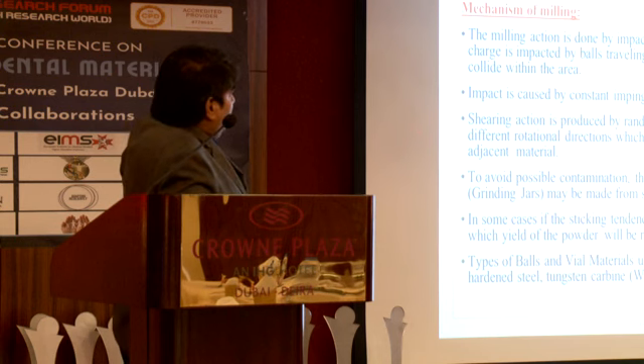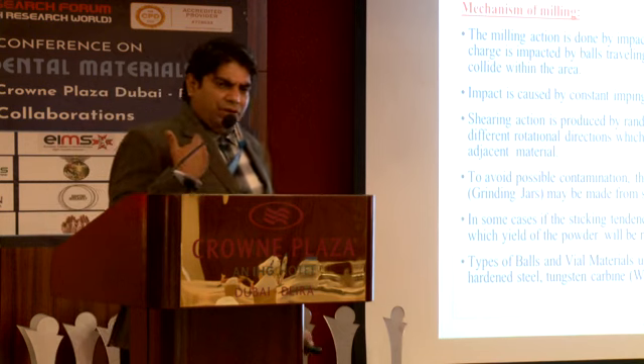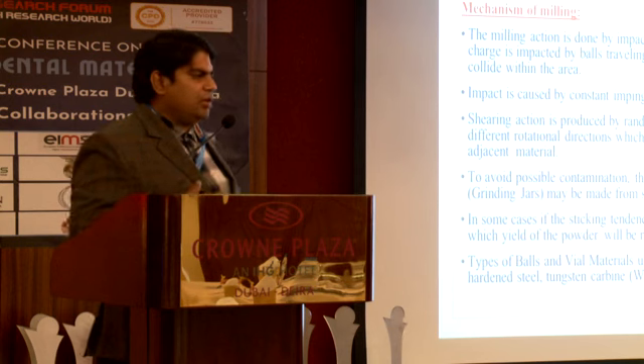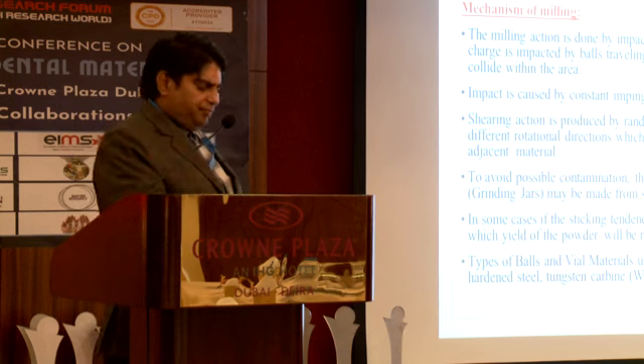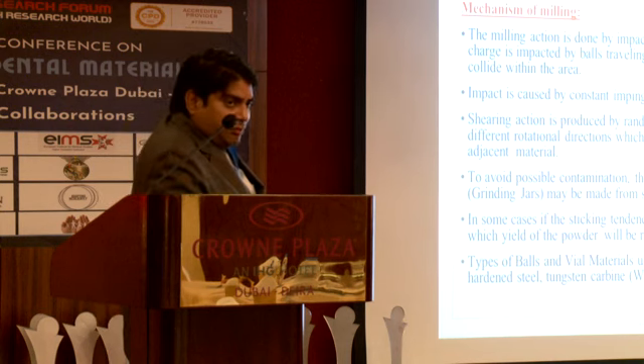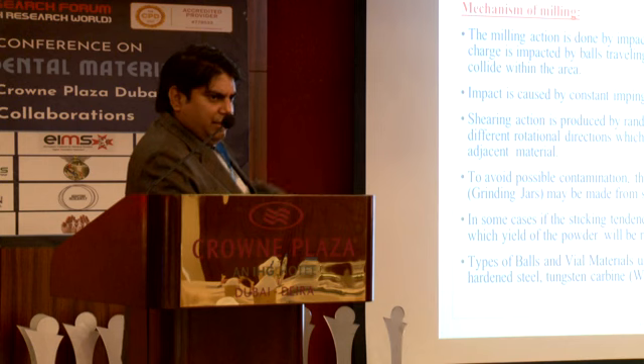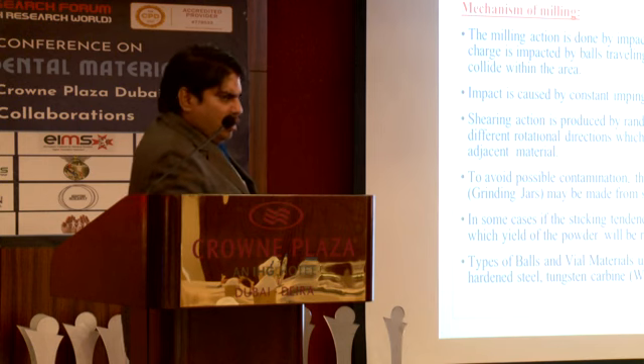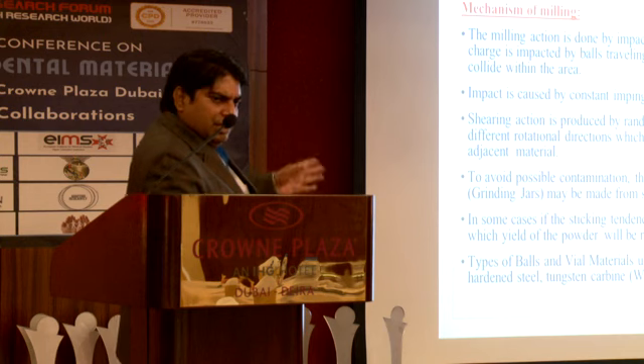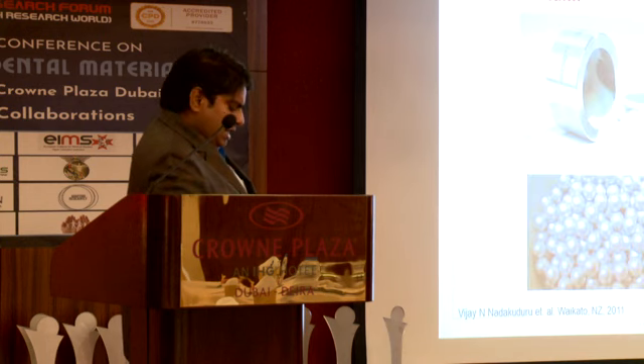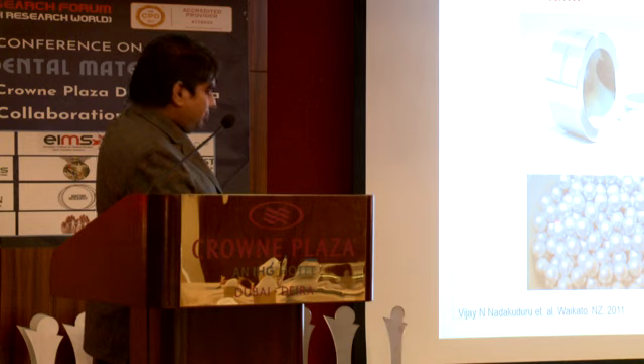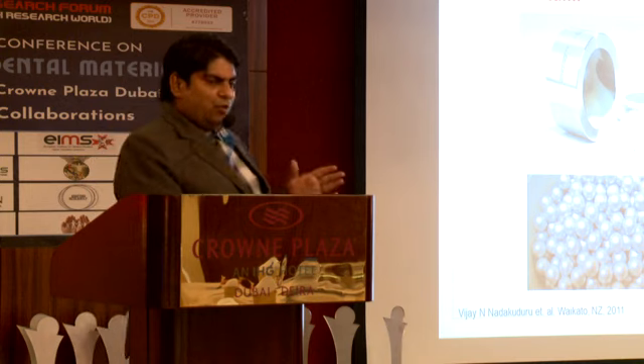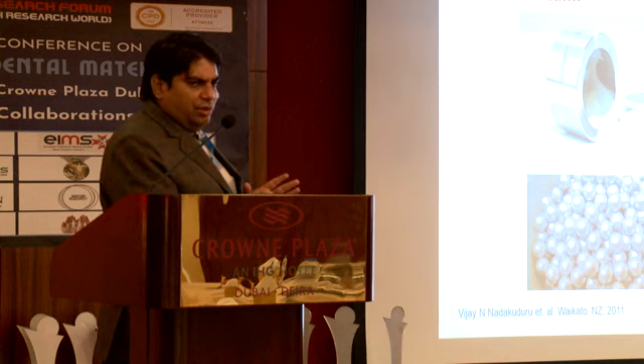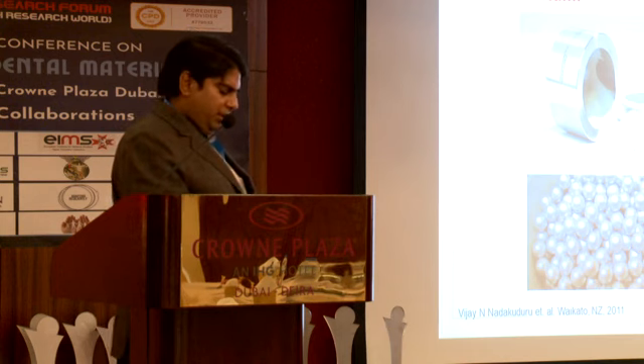This is the mechanism of milling. What happens? In this milling action, different types of forces are involved: shear forces, frictional forces, and impact forces. Because of that, there is a transfer of energy from the balls to powders. So this is the general scenario. There is less sticking in the case of wet milling, and more sticking in the case of dry milling. So you should be careful to maintain the composition while using dry milling, because sticking deviates from the composition.